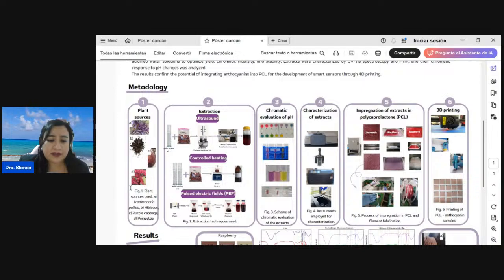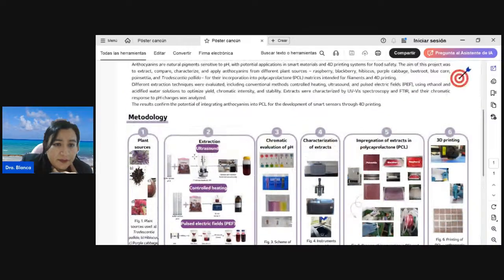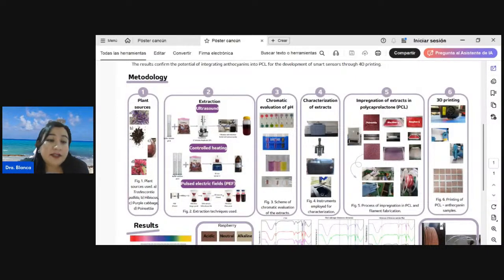these different plants, we extract anthocyanins with different extraction techniques. We use 3 different techniques. We use ultrasound in hibiscus and red cabbage too. We extract with ultrasound probe and bath too, and controlled heating too, and with pulsed electric fields like blackberry, strawberry, and red cabbage too. The extraction process employs ethanol and acidified solution in order to maximize pigment recovery and stability.